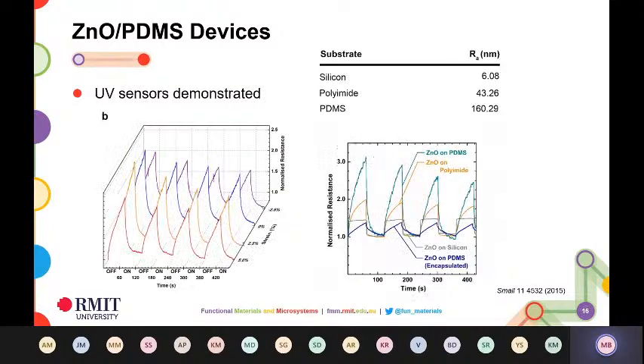And similarly, zinc oxide is quite sensitive to UV. If you do a transmission spectra of zinc oxide, you'll find it's really sensitive in the UV region of the spectrum. And you can see over here, it's behaving in a very linear manner to UV exposure. There's a change in resistance every time the UV light hits it, and then it recovers back to its original state. The reason why these are behaving really well, we attributed back to the fact that there's a piezotronic effect.